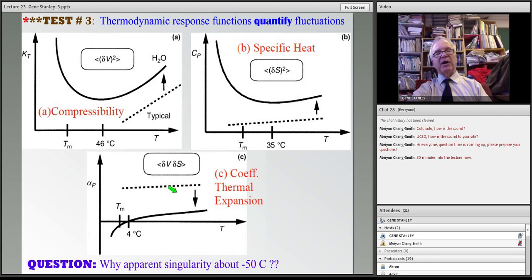And finally, there's something very remarkable, and that's the cross fluctuations of volume, that's this, and entropy, that's that. And these volume entropy cross fluctuations are proportional also to a thermodynamic response function called the coefficient of thermal expansion. And for all materials, this is positive. But we just saw that for water below 4 Celsius, this function goes negative. And all three of these response functions can be fit with the power law with the same fitting temperature, the same apparent singularity temperature of roughly minus 45 Celsius.